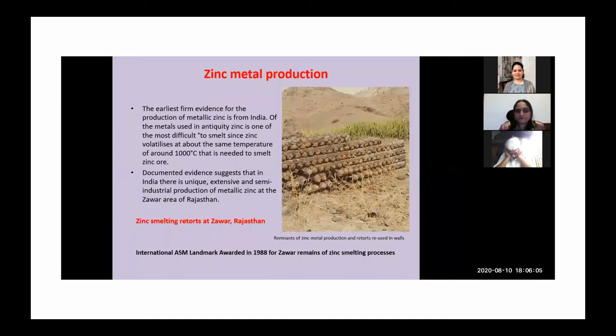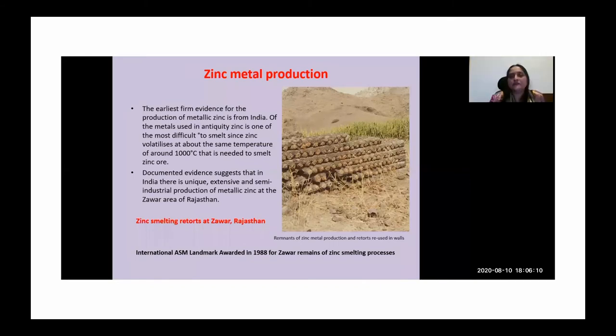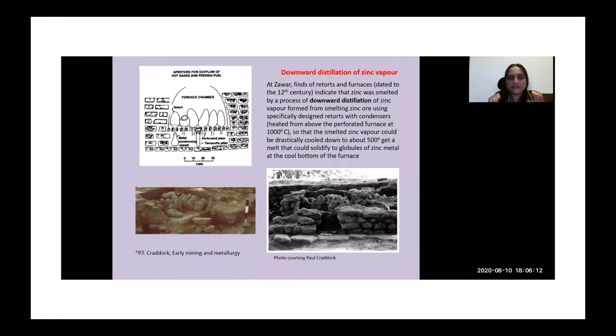And in fact, the ASM Landmark Award was also awarded in 1988 for Zawar for the remains of the zinc smelting process. And typically here at Zawar, there were numerous finds of retorts and furnaces. And the process of smelting of zinc was what is known as downward distillation, where this furnace had two parts. What you normally see is that in the furnace the blast comes into the bottom, but here the furnace was designed such that the koshti, or the furnace, has two parts.